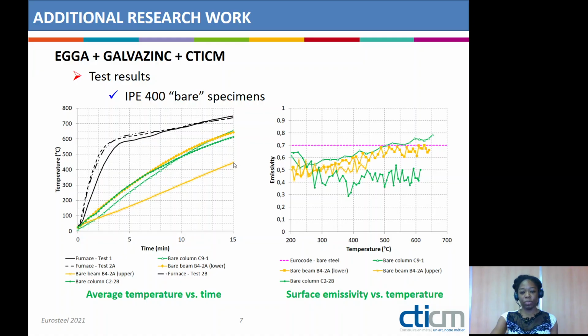Whereas on the upper flange, which was exposed only on 3 sides, you have a temperature that is below 500 Celsius degrees. These values were then used in the reverse method in order to get the equivalent surface emissivity of the specimens. And you can see that the values are mostly less than 0.7, which is the design value of bare steel. And this value stays above 0.5 in general. So even though they are not exactly equal to 0.7, they are rather consistent.